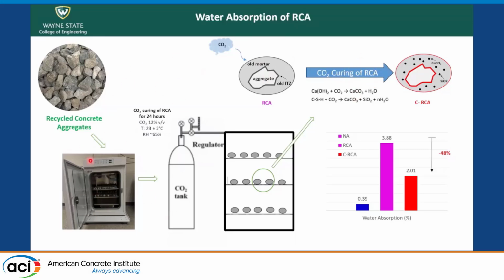The technique that we use is a carbonation chamber. We thoroughly put the RCAs in there, and we induce CO2 for 24 hours. Then after that, we measure the water absorption, which decreased by almost 50%. We have also tried different carbonation times, and we observed that if we CO2 cure the RCAs longer than 24 hours, the water absorption reduction is not that high. We only had marginal increases, so we thought that there's no really good reason to increase this time higher than 24 hours.